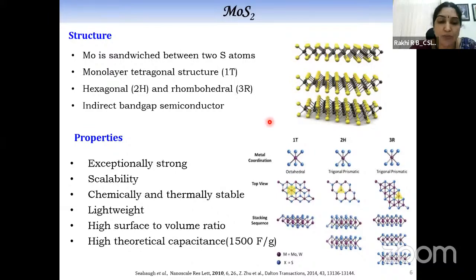Based on the coordination between molybdenum and sulfur in a single layer, MoS2 can exist in 3 polytypes. The first one is the monolayer tetragonal structure, the second one is the hexagonal structure, and then a rhombohedral structure. The monolayer tetragonal structure is very hard to make and is conducting in nature, whereas 2H and 3R are semiconducting in nature, and these are the stable forms of MoS2 found in nature, hexagonal and